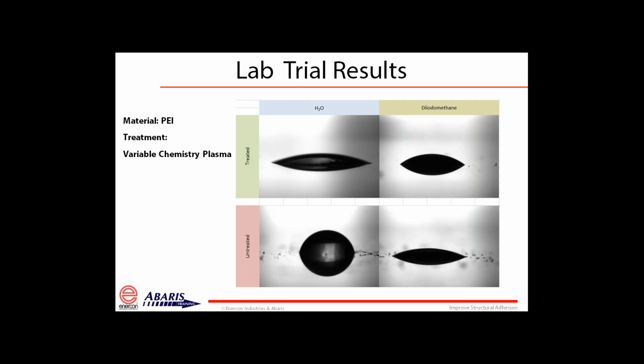So one of the things that we looked at as we were running these results, and we were measuring the surface free energy with that Krüss surface analyzer. What I want you to note here is not only the droplet on the bottom left versus the treated surface on the top, where that's really wetting out, but look at the two bottom pictures and look at the particles of dirt that you see on those bottom two pictures. As we look at the top two, which are treated, see how clean that surface is. So that is one of the effects, not only of the adhesion and the wetting out on this PEI material, but also how we are able to clean the surface. In this case, we used a variable chemistry plasma to run these tests.